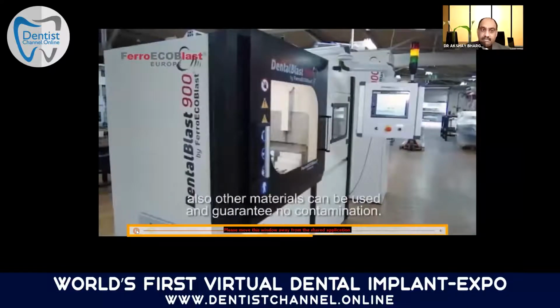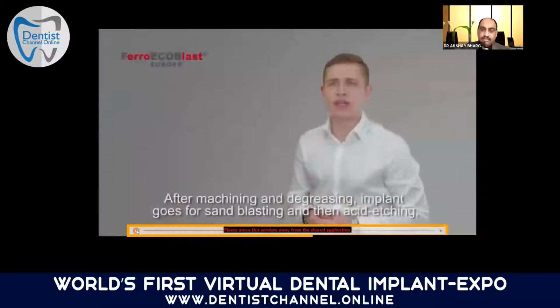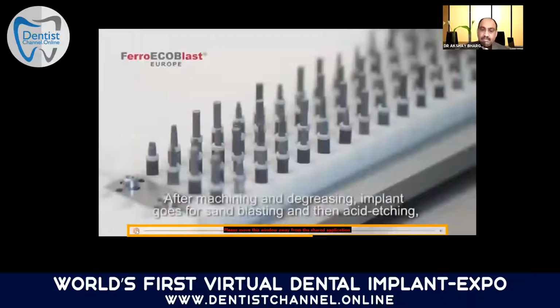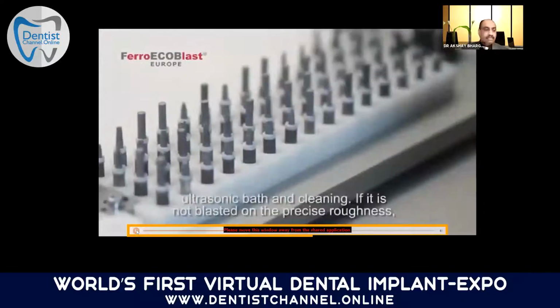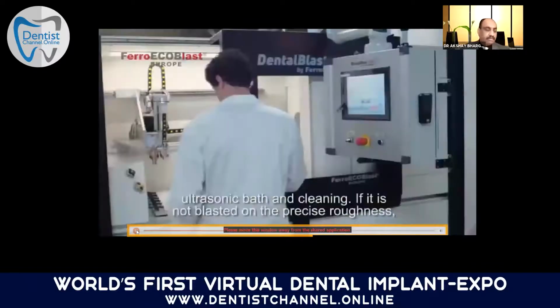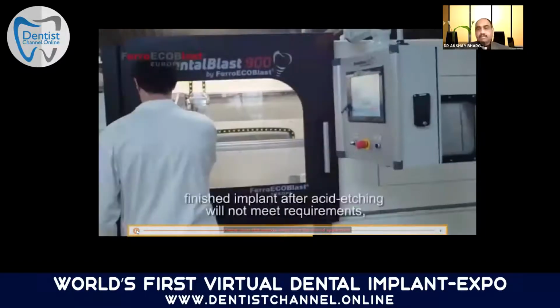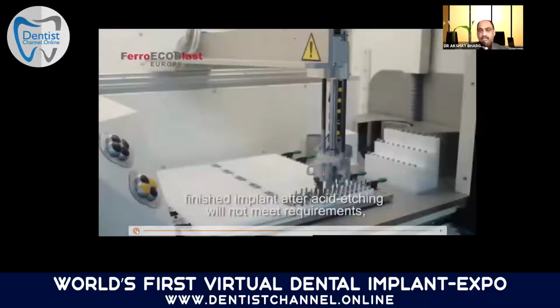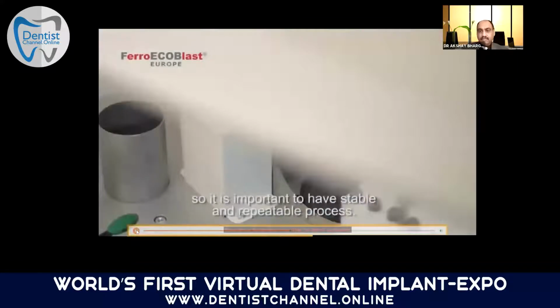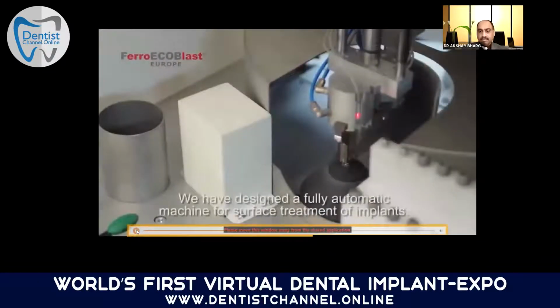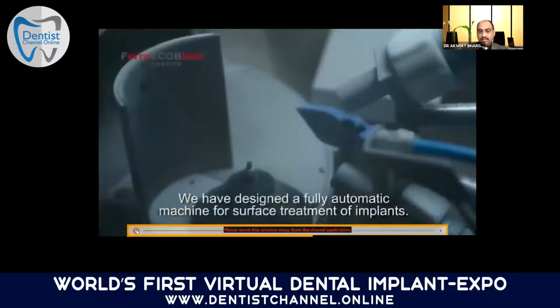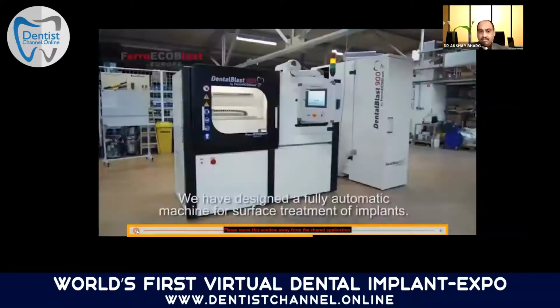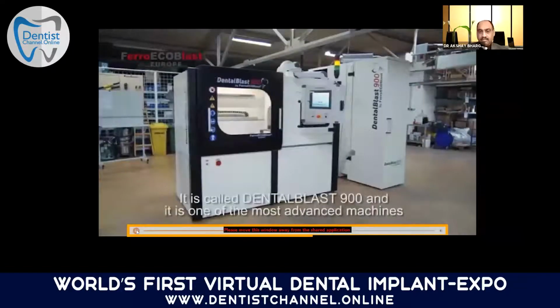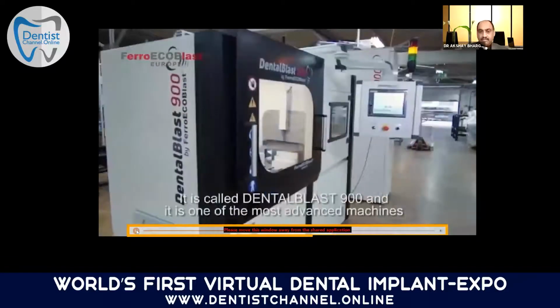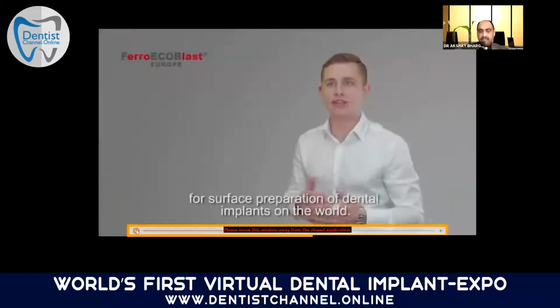After machining and degreasing, the implant goes for blasting, and then for acid etching, ultrasonic bath, and cleaning. If it's not blasted to the precise roughness, finished implants after acid etching will not meet requirements, so it's important to have a stable and repeatable process of sandblasting. Here at FerroECOBlast, we designed a fully automatic machine for surface treatment of implants. It's called Dental Blast 900, and it's one of the most advanced machines for surface preparation of dental implants in the world.